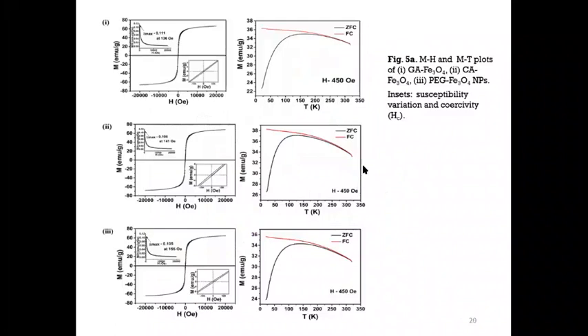All right, so let's go into the magnetic properties of the materials. If you see the magnetic properties, it shows superparamagnetic nature, as the size of the particles is around 10 nanometers, so it is well below the superparamagnetic critical diameter of the particles. And the saturation magnetization is quite high. It's above 60 in almost all the cases. I have given the data in the table.